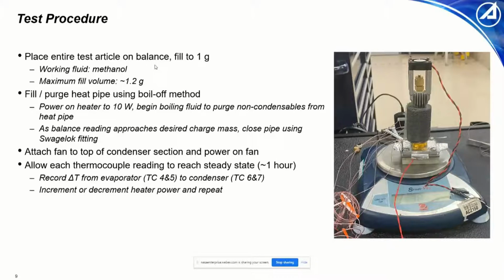We would fill it to 1 gram of methanol, so all of these tests were performed using methanol as our working fluid. The pipe itself had a maximum fill volume of about 1.2 grams, so you can see we fill it almost all the way to the top.